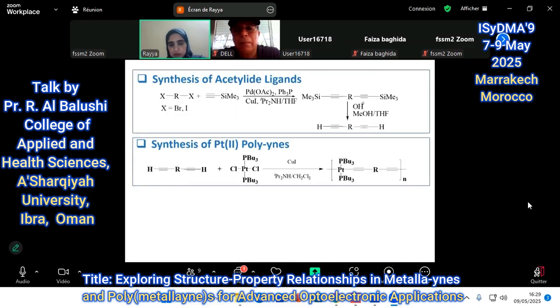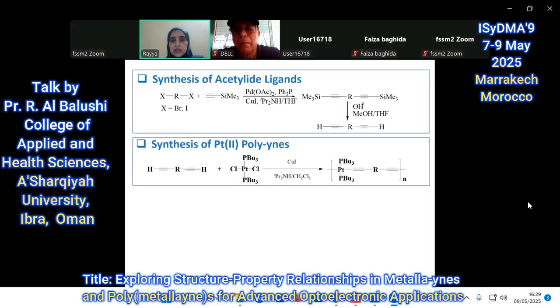Usually in our work, we start the preparation of our polymers by designing and synthesizing our acetylide ligands. So we have the precursor, the dibromide or diiodide, and we react it with the trimethylsilyl acetylene to make the protected ligands. This is a cross-coupling reaction, which of course is very sensitive, and usually we face issues in the yield